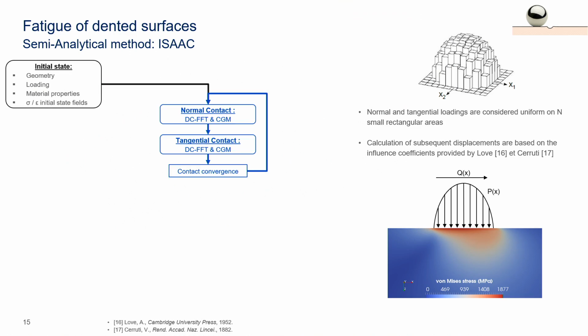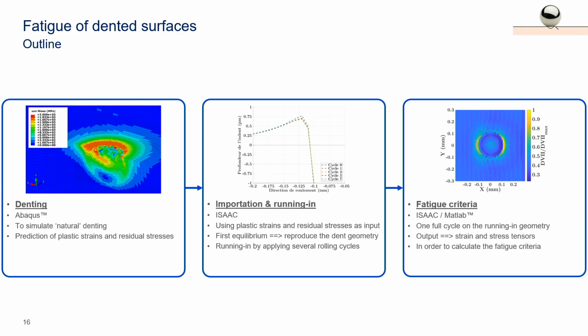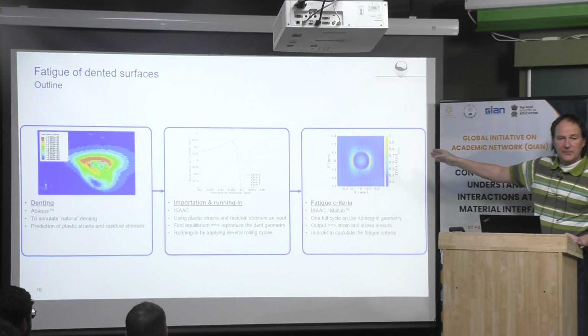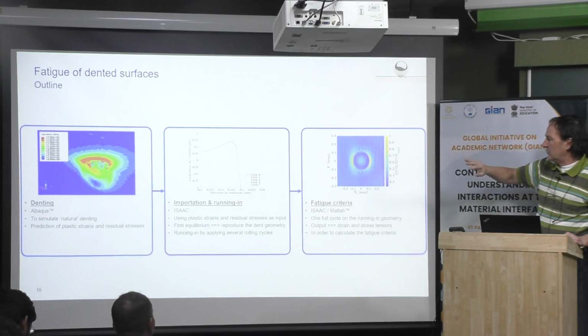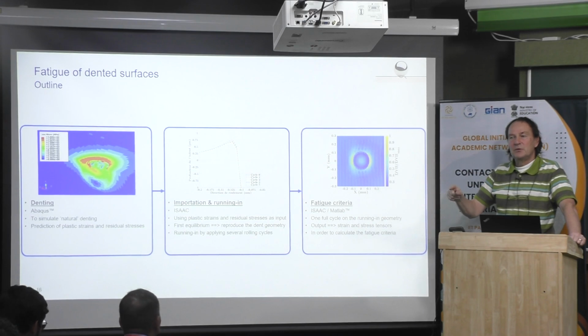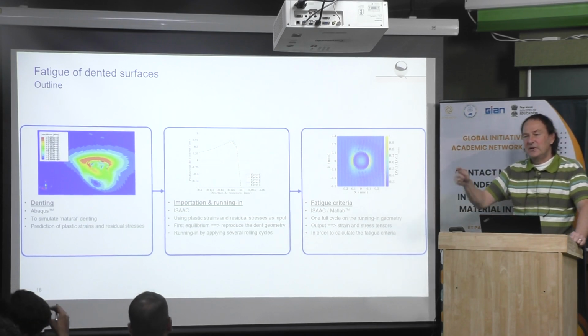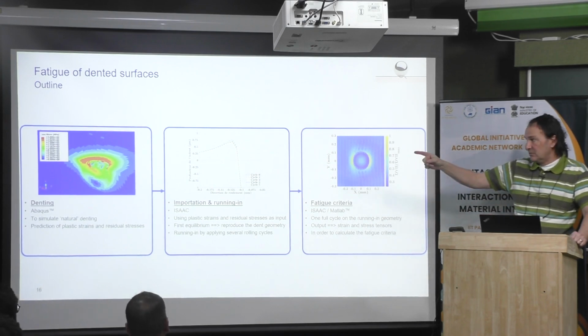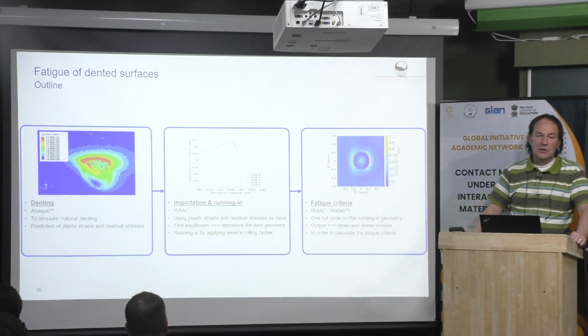Okay, then we use the same tool. Then what we do first is we use a solution from the finite element method, and we transfer the field from that to our model. And then within our model, after, we are able to make a simulation when a ball is rolling on the defect several times. Because by the finite element method, it's too costly. It will be too long. And we just have to transfer the data.